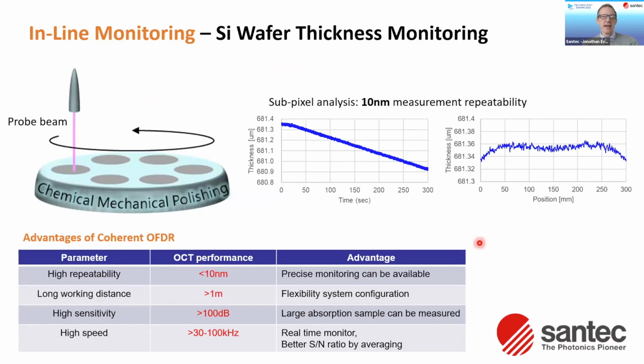The second inline processing application I wanted to discuss was wafer polishing. This is silicon wafer polishing, and our probe beam comes down from the top. You've got your wafers in the polishing system. They go around and they're gradually ground down. The key takeaway is that we can get tremendous high resolution on the measurement of the thickness. This plot is the thickness versus time, and you can see it decreasing as the wafer gets thinner. The actual resolution we're getting on this measurement is 10 nanometers, so we're really into that sub-micron resolution. And you can do that across the whole width of this 300 millimeter silicon wafer. Again, a nice use of this technology, which we first used for medical imaging, into industrial applications.